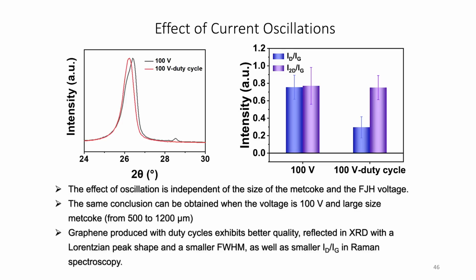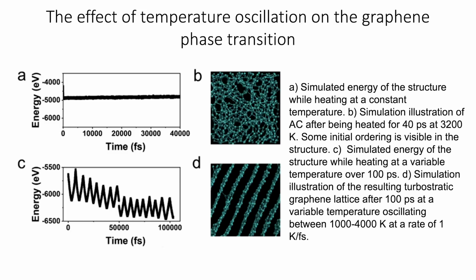This is the peak height of the 2D, reflective of the purity of the material. You get a much better material with these duty cycles, and that's exactly what we had modeled. This is the simulation, when you don't have a duty cycle versus when you do have the duty cycle, which helps these sheets to order and arrange. So just the typical 60 hertz pulsing is helping the system.